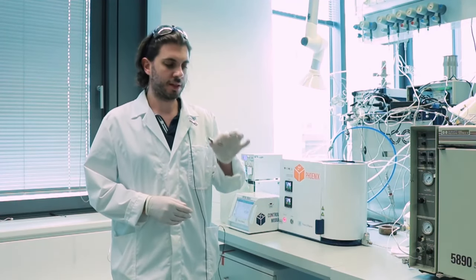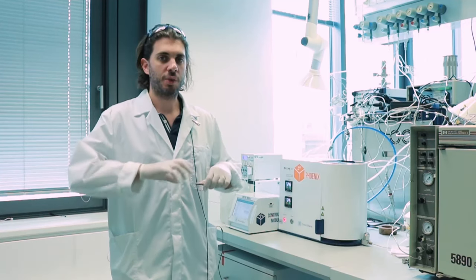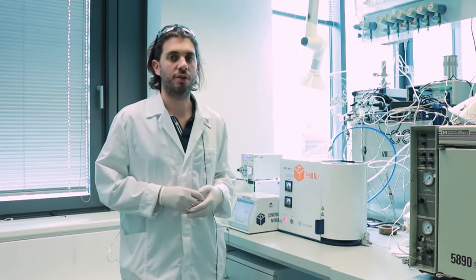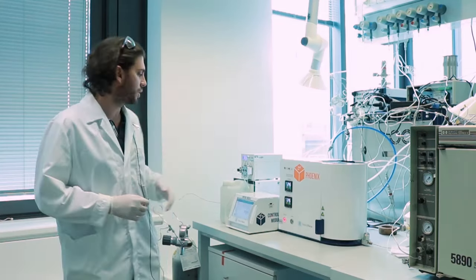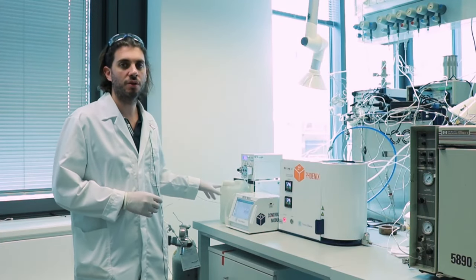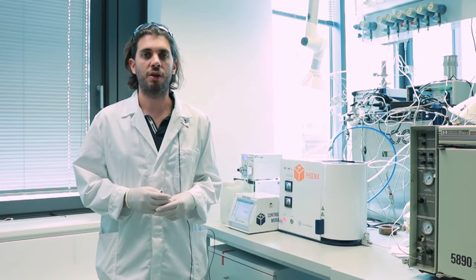We introduce the catalyst in this cartridge. Then we seal it and we set up the reactor. The process works in flow using an aqueous solution of the alcohol to be oxidized with oxygen, and spinels containing cobalt as the main metal are especially good catalysts for the reaction.